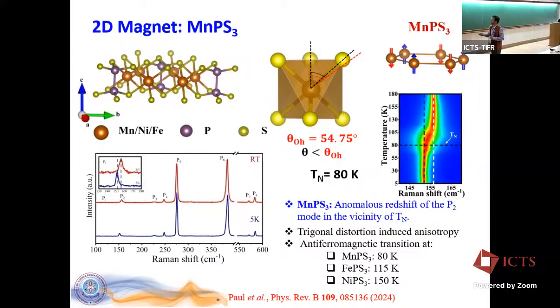And P1 also shows a similar kind of behavior. So here, what I'm trying to tell you, this is the color map where temperature versus frequency of this P2 is captured, and also the color basically tells us the intensity of the mode. You can see very clearly this is almost constant above the Néel temperature in the paramagnetic phase, and below the Néel temperature, it has shifted to this value. Okay, this shift is the signature in Raman for the antiferromagnetic transition.